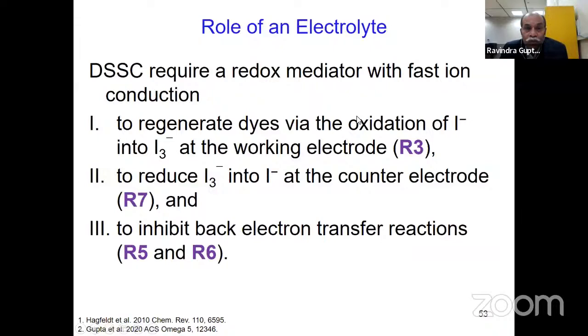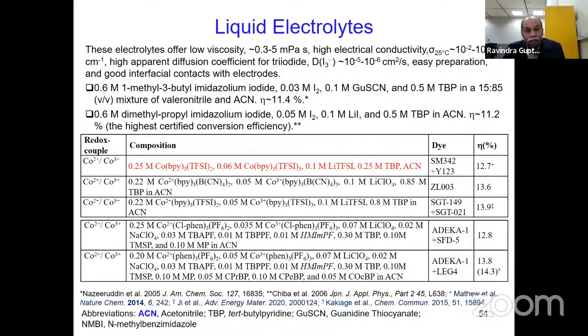And what is the role of electrolyte? So it regenerates dyes via the oxidation of iodide into triiodide at the working electrode. It reduces triiodide into iodide at the counter electrode, and it inhibits the back electron transfers, like recombination. We don't want any recombination, which is not good for any type of solar cells. So these are the liquid electrolytes, and we have at present 11.4% for this type of electrolytes.